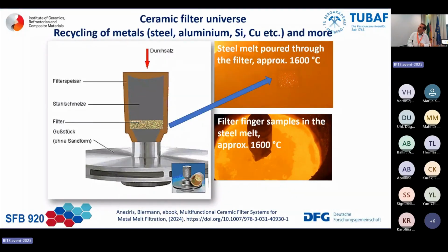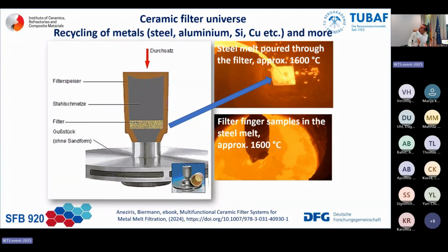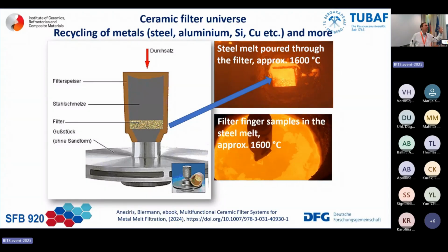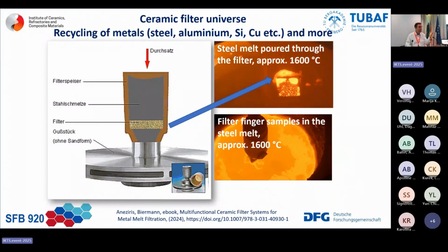Of course, the steel melt can be cleaned through the filter, or you can also use carbon bonded alumina and make bubbling in the melt. And then you can, via buoyancy forces, select and pick up inclusions, like a porous plug is doing.